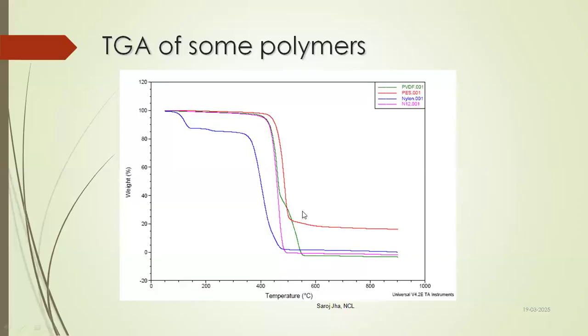So this is how you can read a simple TGA curve, which gives you information about: is there any water content or volatiles in your sample? What is the degradation onset of your sample? Is your degradation 2-stage or 1-stage? Is there any residue remaining in your sample? Very important information for product design.